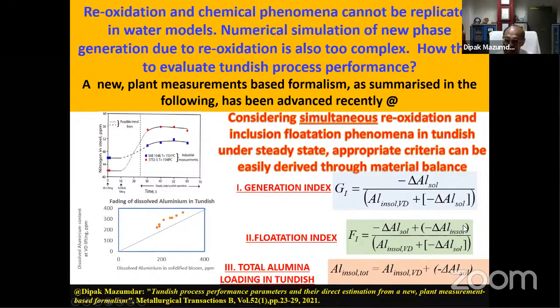Similarly, the flotation part is this particular component. If you divide whatever is floated by the total inclusion loading, you get the flotation index, and these indices vary from 0 to 1. This gives you the total inclusion loading, where you can see this is the steelmaking component. This value will tell us how good our steelmaking process has been, and this will tell us how good our Tundish processing has been. Two together will determine the total insoluble aluminum content in the Tundish, or the inclusion content.